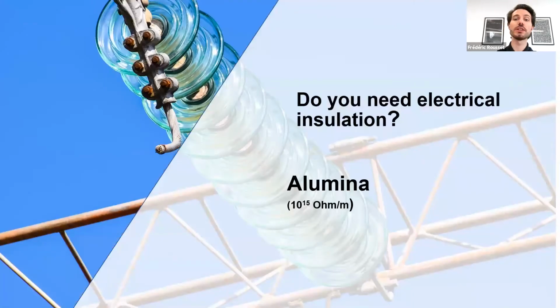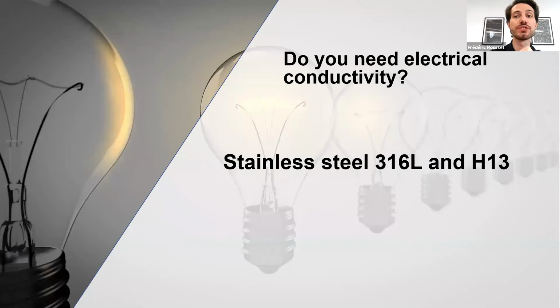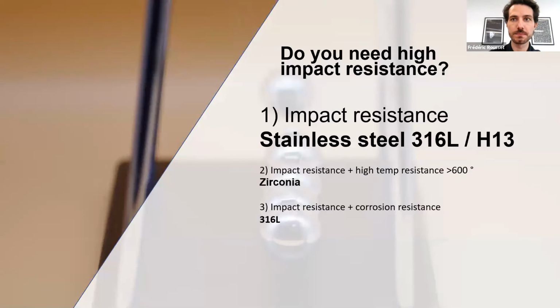For any electrical insulation, you can use the alumina. There are no questions about that. For electrical conductivity, you can use the metals that we have available at Nanoe. For high impact resistance, the best ones are the metals, so the stainless steel and the tool steel. If you need high temperature resistance, so over 600 degrees, where the metals are a bit less advantageous, you can use the zirconia. And if you need some corrosion resistance, you can use the stainless steel.